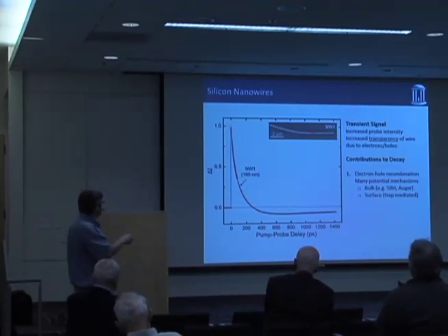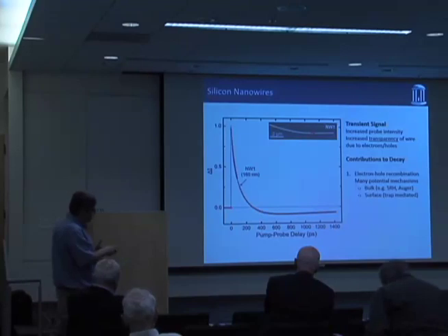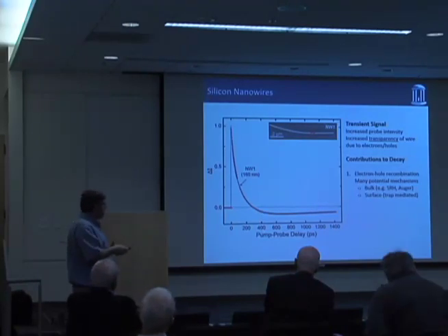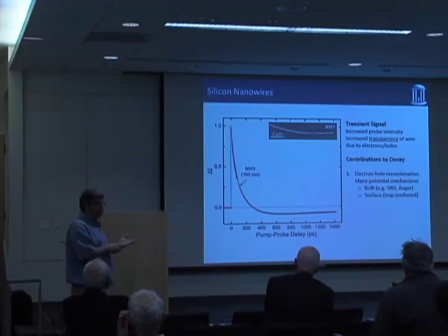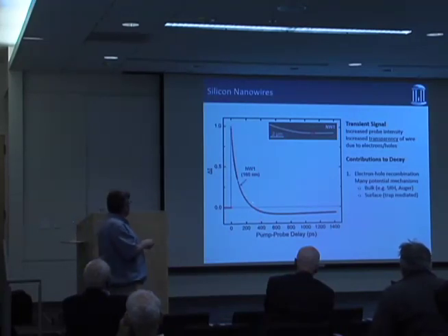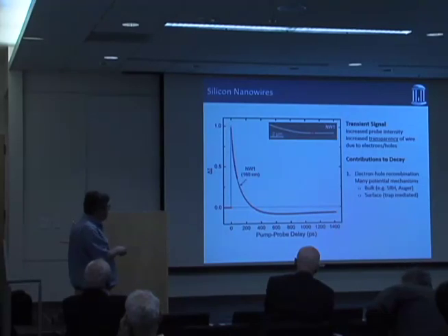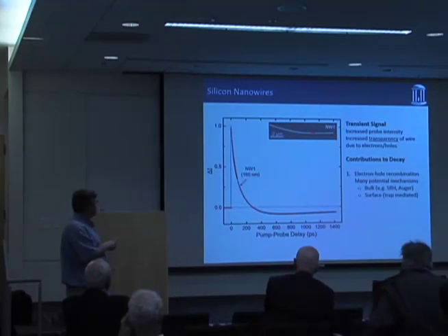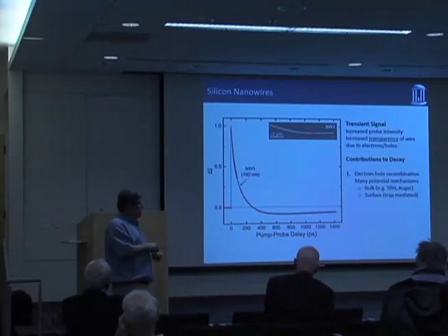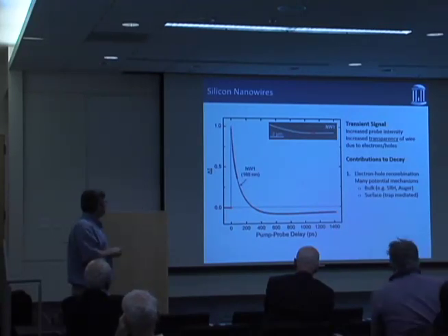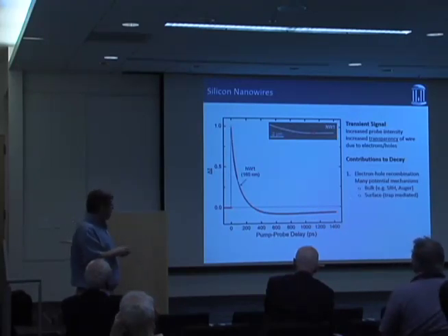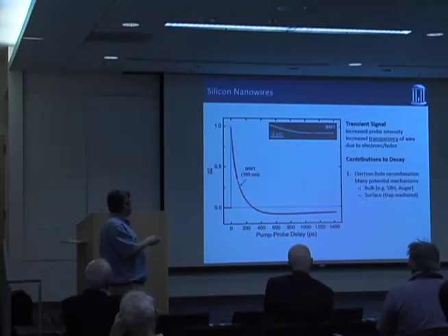And in long times, it turns into a slight absorptive component, which we think has to do with trapped carriers, is one possibility. Another possibility would be that it has to do with thermal changes or thermal effects. But whatever it is, this long-lived absorptive signal is there, and it lives for a long time, and in some respects I'm not really interested in it. What I'm really interested in is the decay of this fast component. And that decay reflects the recombination time of those electrons with the holes. And this can happen through lots of mechanisms. It could be Shockley-Read-Hall, Auger recombination. It also can take place at the surfaces.